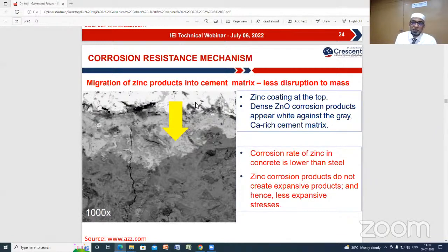Here, in zinc corrosion, zinc also corrodes to protect the steel, but it is a powdery type of material. These zinc powders can penetrate inside and sometimes close the pores in the concrete microstructure. So this is an added advantage if we go for galvanized rebars. In addition to the protection of steel, the zinc corrosion products travel through the concrete and close the pores. This is clearly visible in this SEM picture.